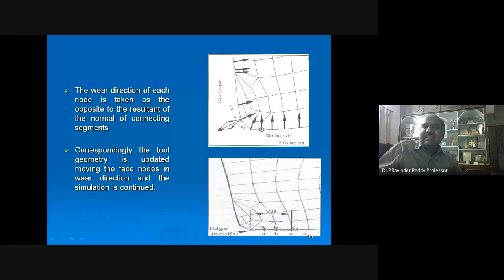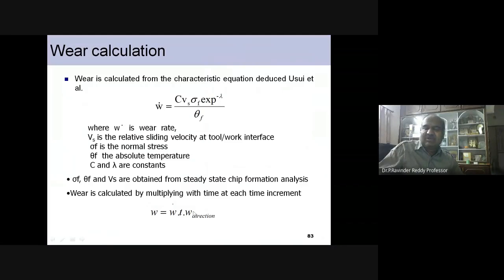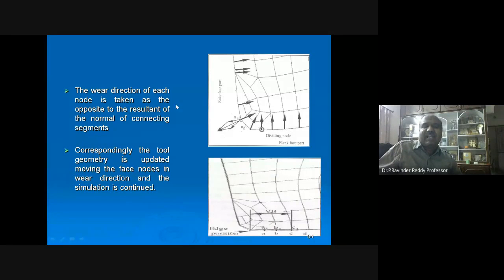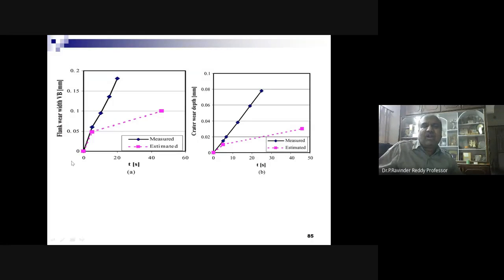These are the phases where the nodes are identified, and the normal to that, when you couple to the previous, they are going to correspond to the direction of wear, which we can take from those nodes. The wear direction of each node is taken as the opposite to the resultant of the normals of connecting segments. Corresponding to it, the tool geometry is updated, moving the face nodes in wear direction, and the simulation is continued. And we can plot the flank wear width measured and estimated, and here also crater wear depth against the time. So we can calculate the rate of that, and we can showcase.